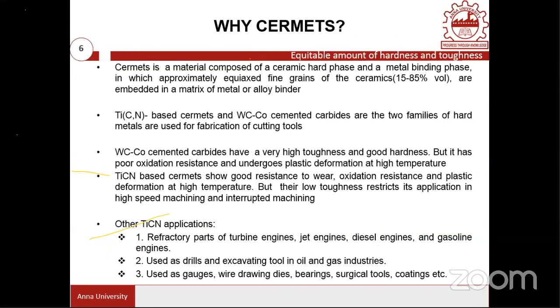And the ceramic composition, this CERMET is a ceramic material, normally equiaxed fine grains of ceramic, roughly varying from 15 to 85% in the binder alloy. Normally, when you compare this titanium carbonitride CERMETS with the tungsten carbide cobalt, the tungsten carbide cobalt composition is basically a cemented carbide, which is represented as a hard material. Now we are giving the name cemented carbide, but there are two families of hard material. TiCN based CERMETS are a hard material. Another branch is tungsten carbide based cemented carbide material.